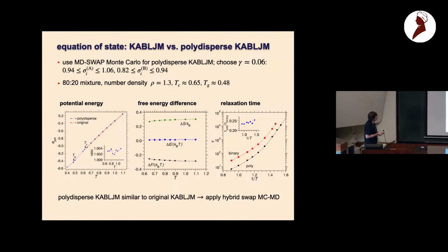Also the relaxation time - the polydisperse system is slightly faster, but the ratio of relaxation times is more or less constant in this area. So we can expect that the polydisperse system is, with respect to the physical properties, very similar to the original binary Lennard-Jones mixture. And now we can apply the hybrid swap Monte Carlo MD technique.